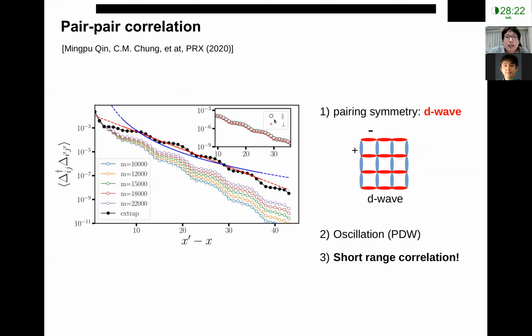The first thing to observe is the pairing symmetry of the system. In high TC, we expect the pairing should have D-wave symmetry, meaning the correlation between the vertical bond and the horizontal bond should be symmetric but with an opposite sign. This stays true for all vertical and horizontal bonds.